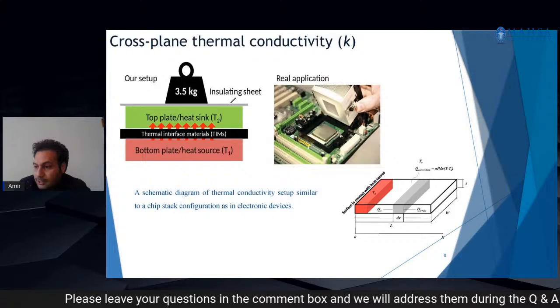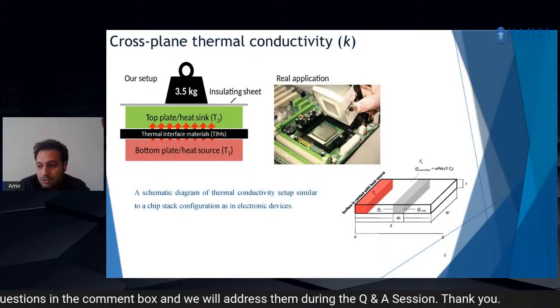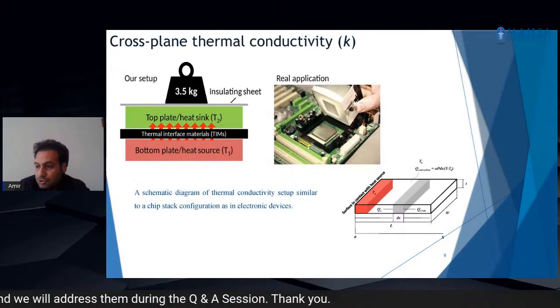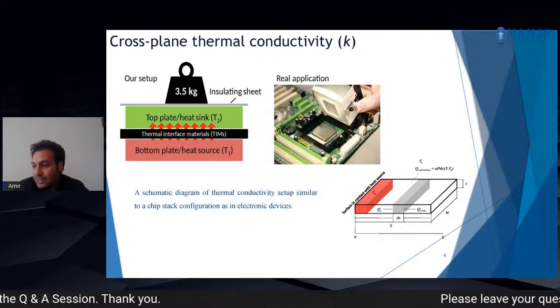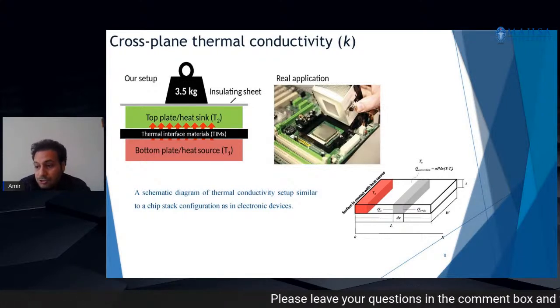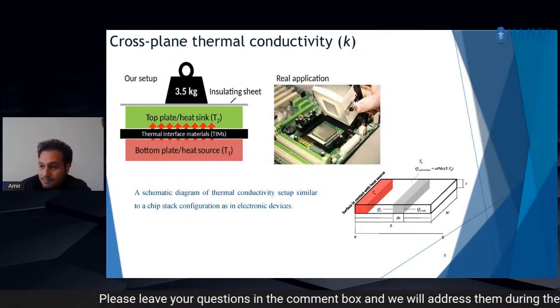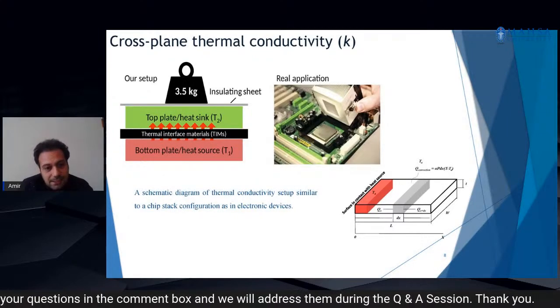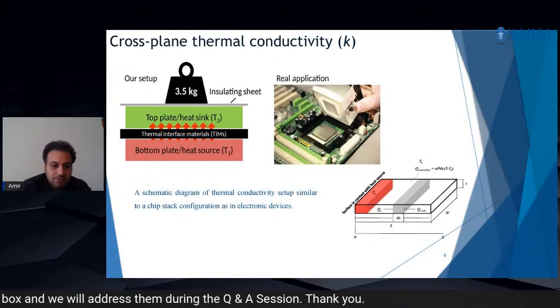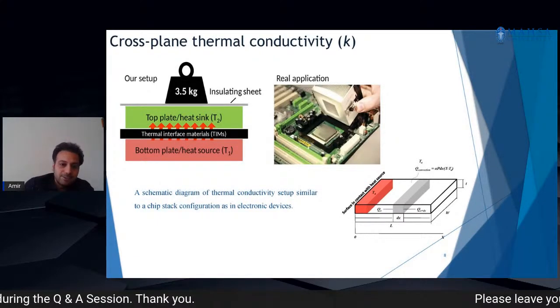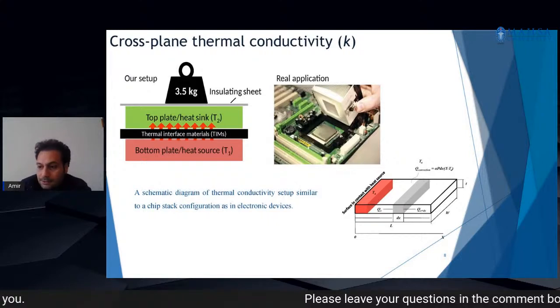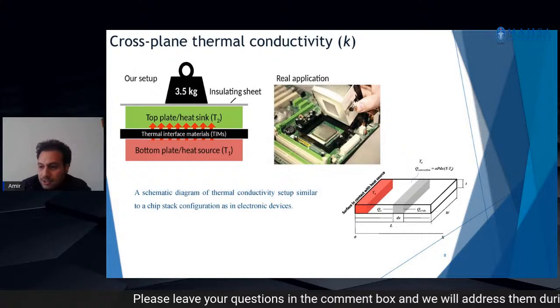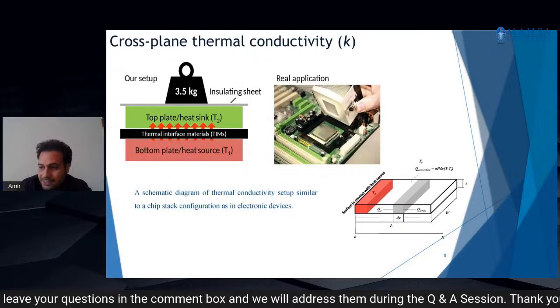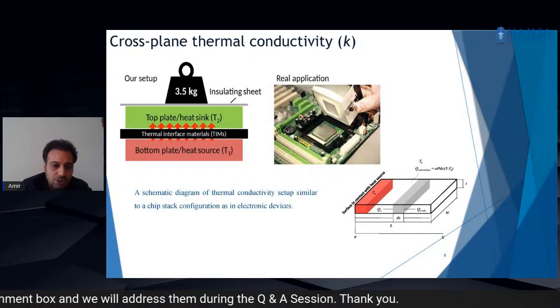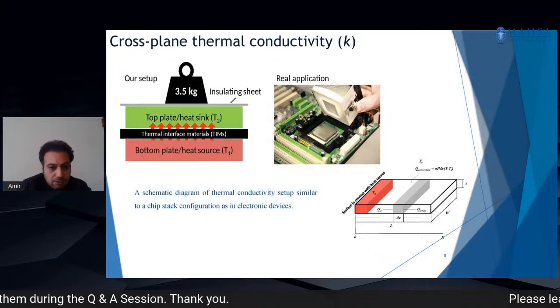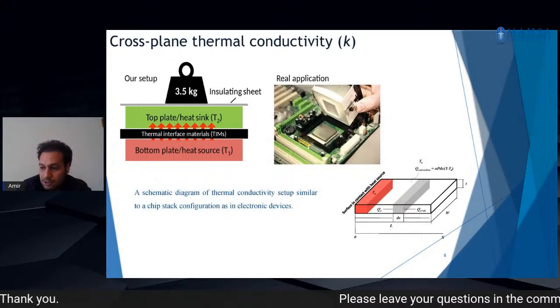An insulating Teflon sheet with 2 millimeter thickness was also used between the top steel block and the pressing weight to avoid any thermal dissipation. We use the weight on top to be sure that we have enough pressure to ensure heat transfer between the two blocks. And on the right side, the surface heat transfer or temperature distribution was also estimated by a theoretical model. We are trying to show that our real experiment is similar to the theoretical model.